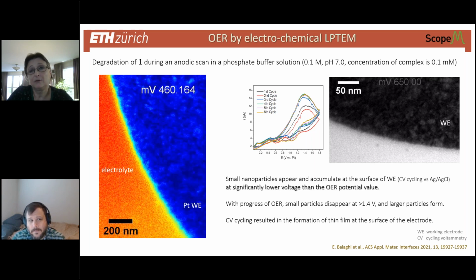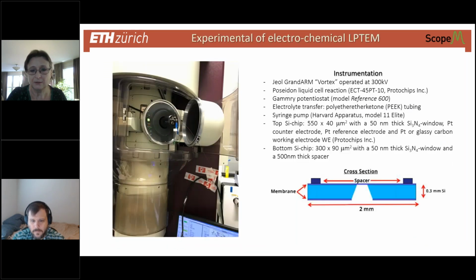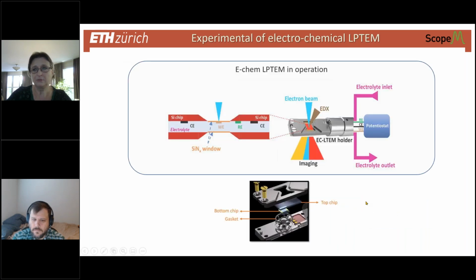Experimentally, if I use platinum, it's really easy to mount. You assemble the cell and look at the binocular, and you have to align two windows. You have two chips, a bottom chip and a top chip, and the top chip has a very narrow, slim window. You have to align it over the window in the bottom chip, and inside this window there is an electrode. You can see it in the binocular, and you have to align those things without fracturing the silicon nitride membrane. So platinum I could see, but the glassy carbon electrode I couldn't see in the binocular.